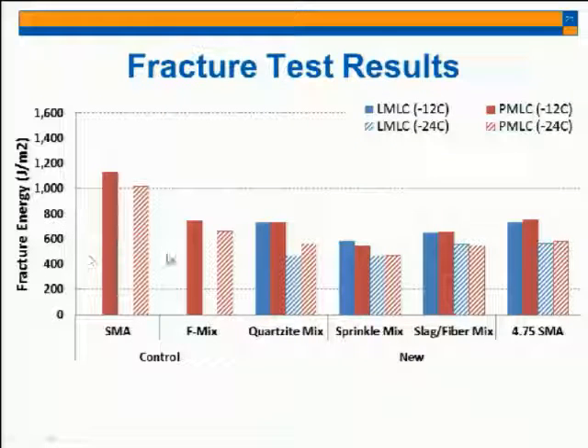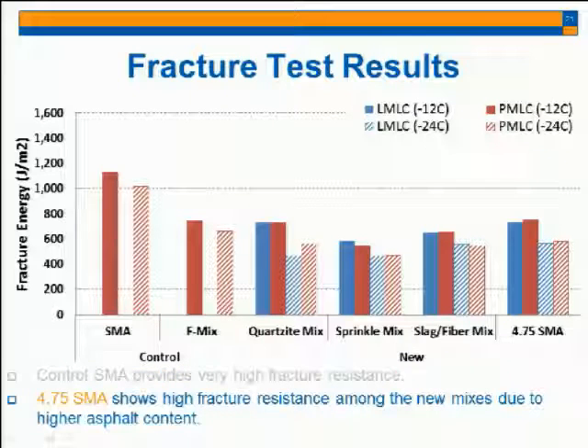Significantly, the control SMA mixture provided the highest fracture energy, but the sprinkle mix was the lowest because we just used the regular or cheap materials for the sprinkle mix, but we spread the sprinkle chips like chocolate chips in a cookie. But the 4.75 SMA mixture showed the higher fracture resistance among the new mixtures due to the higher asphalt content. As I mentioned before, we were expecting this slag fiber mixture to have the higher fracture energy because the fiber holds the materials when we do the fracture test. But still, it looks relatively lower than 4.75 SMA.